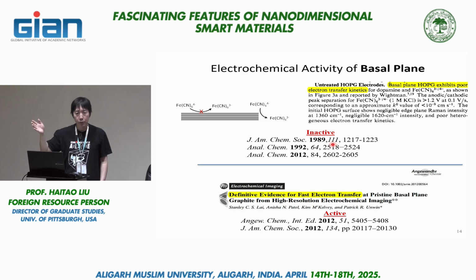So electrochemists have been using basal plane graphite as a model electrode for quite some time. In the 1980s, there was quite a lot of research in understanding the fundamental electrochemical activity of basal plane graphite versus the edge. The edge is the cross-section here. The difference between the two, as I said, is that the basal plane doesn't have any chemical functionalization, but the edge plane does, because you break the carbon lattice, so there are a lot of oxygen functional groups there.